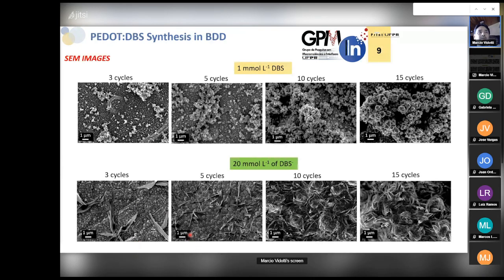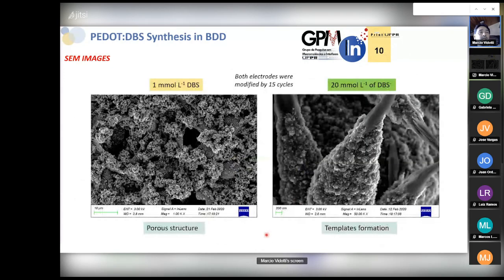And by increasing the polymerization of the material, we can observe a very different structure or morphology compared with the material electropolymerized without these templates. Taking a closer look at this material, for 15 cycles we can observe this porous structure, as I showed before, and in the presence of the DBS structures, a kind of thin plate is being formed with the PEDOT growing exactly on these kinds of horns. I don't know how to say the word for that, but it's quite interesting because it really forms a template for the growth of the PEDOT. And that's the reason why we have such different electrochemical responses, as I showed before.